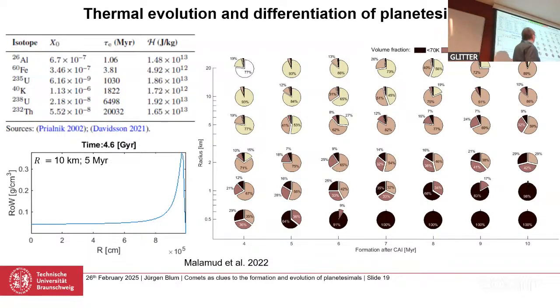And we did that for many, many radii, starting at a half kilometer, up to 20 kilometers, at many different formation times, 4, 5, 6, 7, and so on, million years after CAI. And the pie charts here tell you what percentage of the body's volume reached temperatures given at the limits here. So the black is below 70 K, never heated. You see 70% is, if you have a very small body, and it forms very late, all the radioactive nuclei basically have decayed, and everything stays low in temperature.